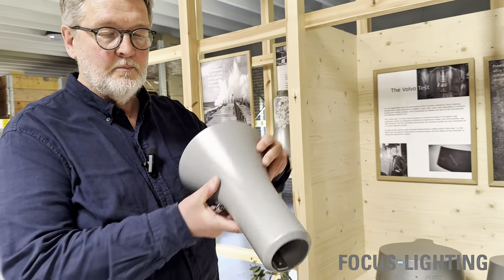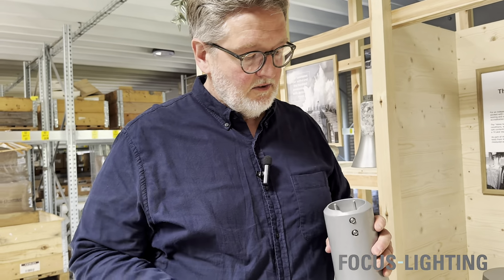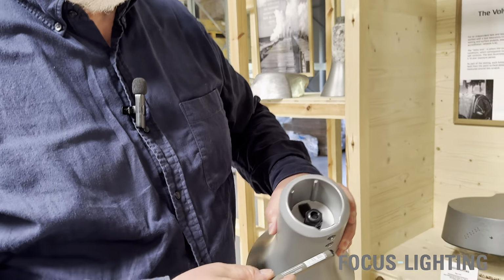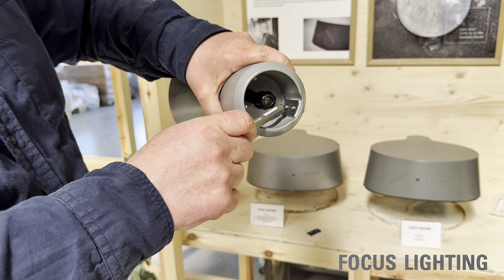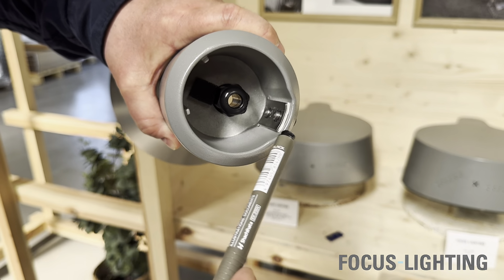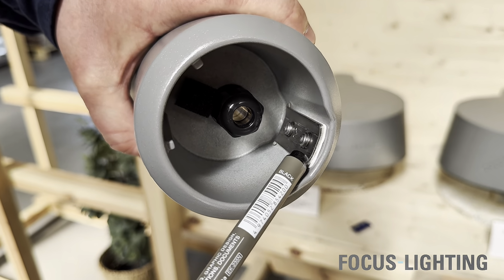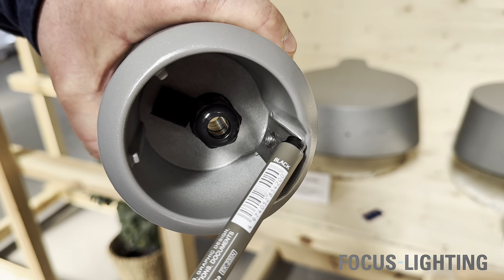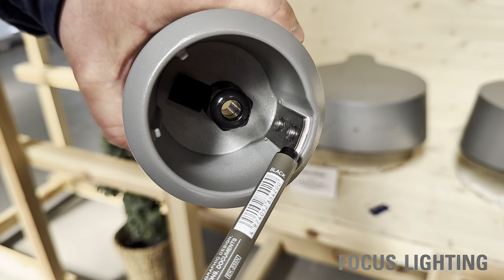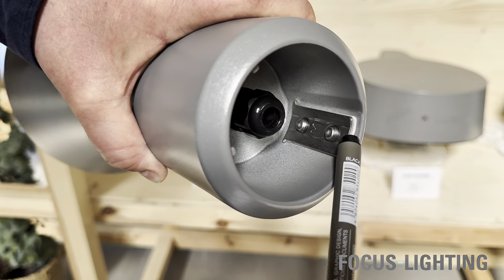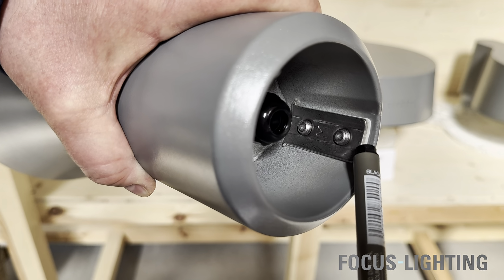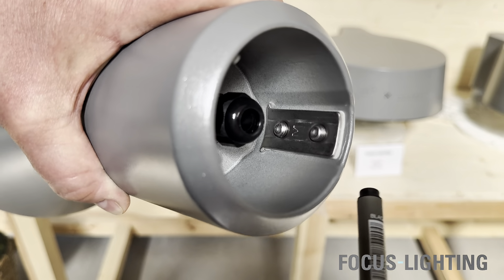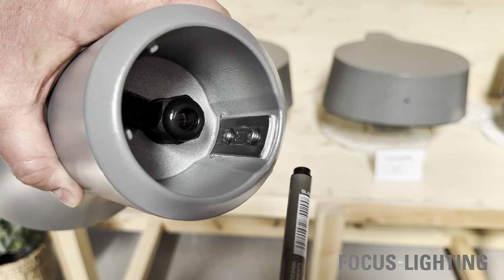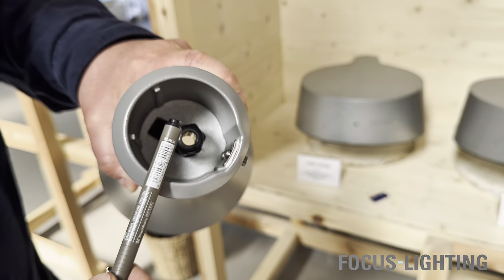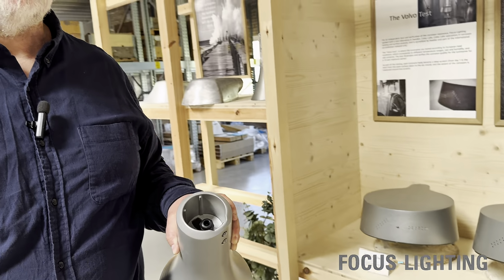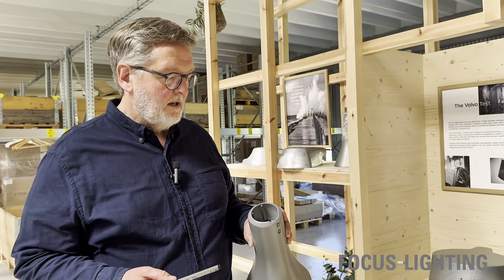So if we stay with the topic of galvanic corrosion, then one of the measures that we have taken on the same luminaire is that we have the stainless steel screws here, but on the inside we have a stainless steel plate. And then behind the stainless steel plate, we have a protective tape that cuts the touching to the aluminum housing away. So there's actually no physical connection between the screws and the aluminum housing. That's one of the galvanic corrosion measures that we have taken.